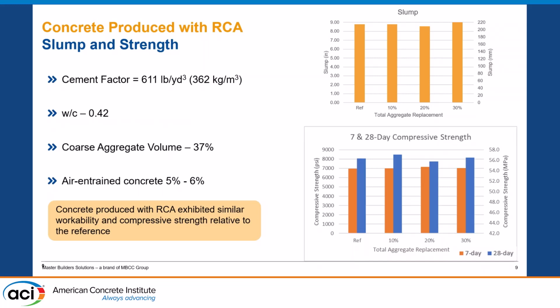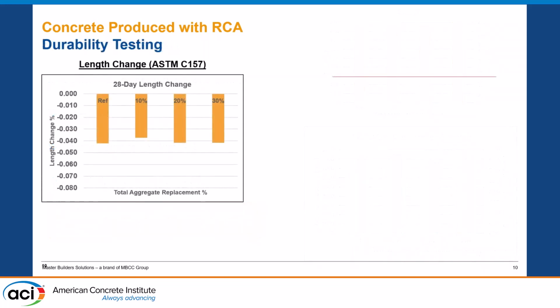But one of the questions that our customers were also asking is, okay, I understand that that slump doesn't vary much, and for that we can also always add a little bit more water reducer or water, and we see that the strengths are pretty decent. And one of the characteristics is that by not having to go through the fracturing or the crushing process, those aggregates tend to behave in a little different manner. But that's not all of it. Durability is also a very important aspect of concrete. So we ran a few durability studies as well.